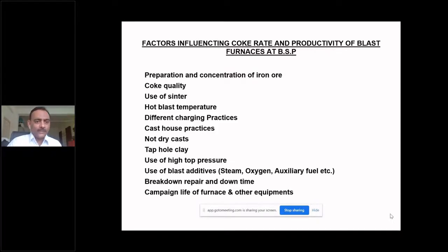Use of high top pressure: we are sending hot air from the lower level of the furnace. When it goes inside, it reacts with the carbon and forms carbon monoxide. Carbon monoxide which goes upward will come in contact with Fe2O3, iron ore, coming downwards. So the reaction between gases and solid should be more, but we are sending this hot air, which is called hot blast, in a very pressurized manner, so it will not be retained too much time inside the furnace. But if we stop the outward journey of hot air, which is now converted into gas, by a wall for some time, the gases inside the furnace will be retained for some time, just like the concept of a cooker.